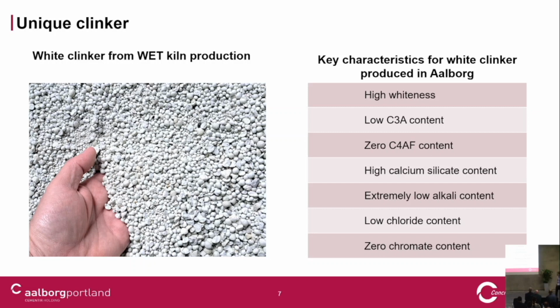Extremely low alkali content. When we say low alkali in Europe, you think about a cement that has 0.6 or less percent of alkalis. We have less than 0.2% of alkali. Extremely low chloride content, less than 0.01.